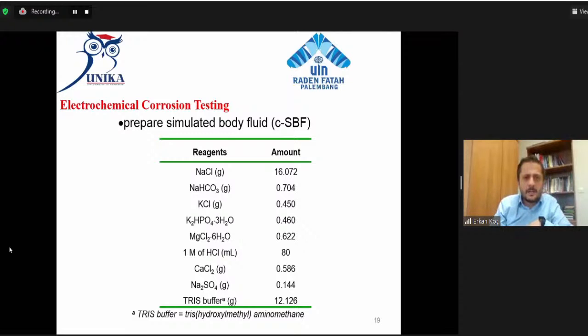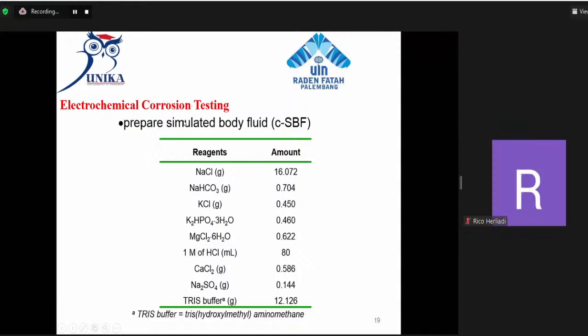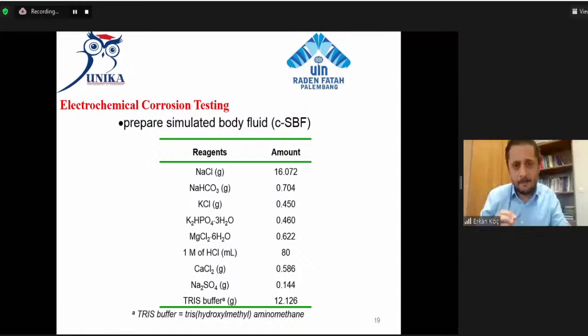And here is simulated body fluid. The in vitro corrosion studies were carried out in simulated body fluid maintained at a temperature of 37 degrees Celsius and pH 7.4. The composition of SBF is shown here. The solution was buffered by tris hydroxymethyl aminomethane.